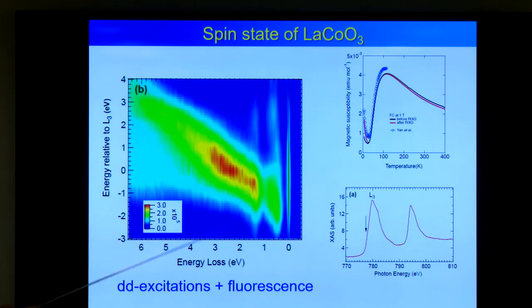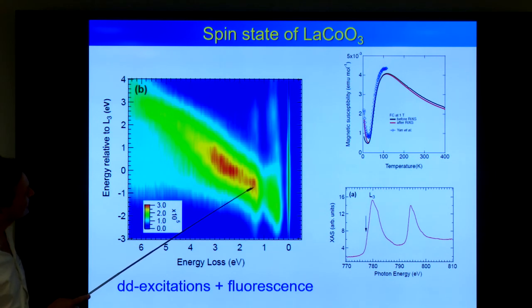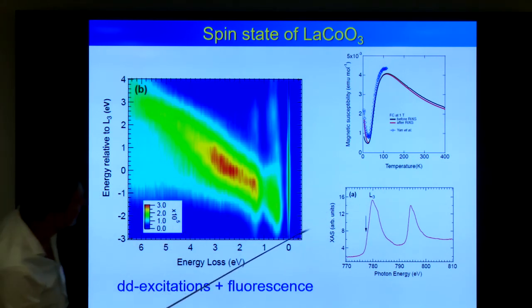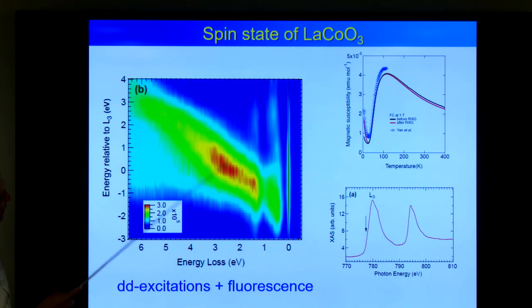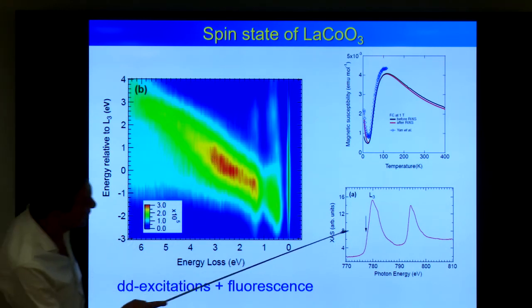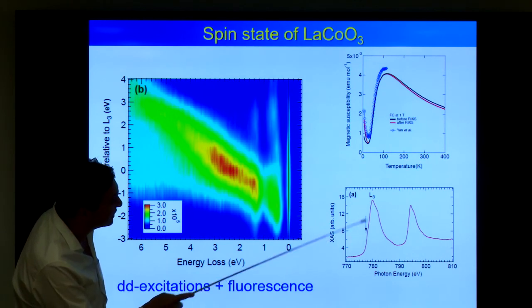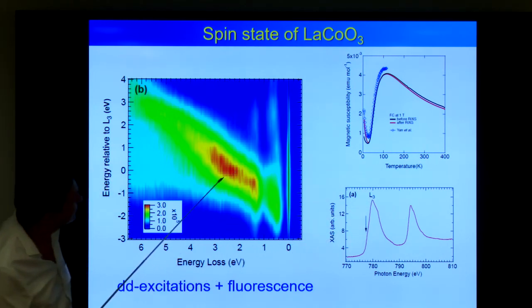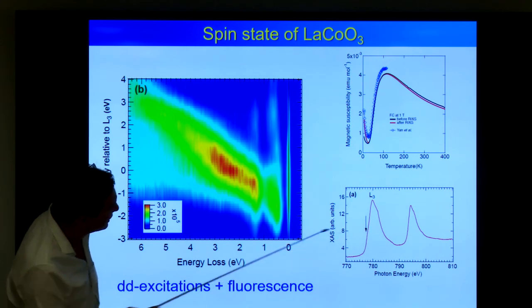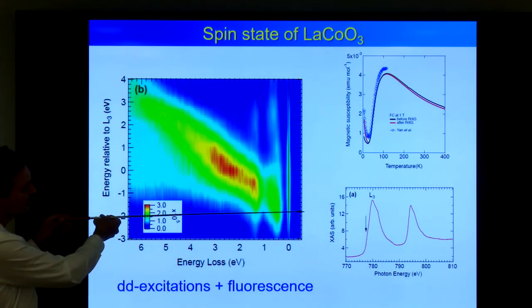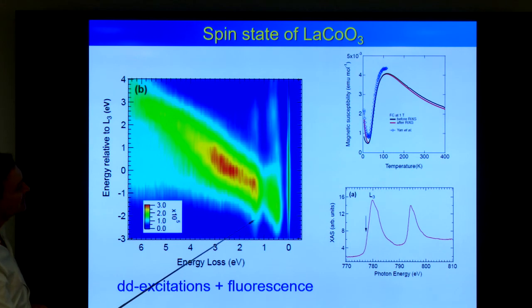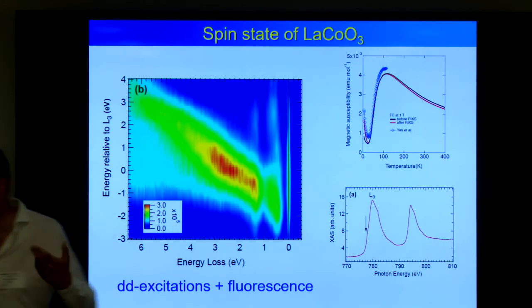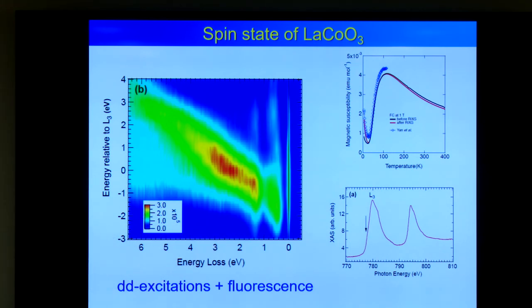So if you do those experiments on solids, this is the RIXS graph. Zero is the peak position of the L3, and this is the energy loss. And here you see this large blob, and that's fluorescence. So that's not something we like to analyze. So for the temperature-dependent experiments, we do not go to the maximum of the L3 because then we see mainly fluorescence, but we go a little bit before. So somewhere here. If you make a cut here, you don't have fluorescence and you still have your dd excitations. And then we heat up, and then you can see the low spin, high spin transition point.